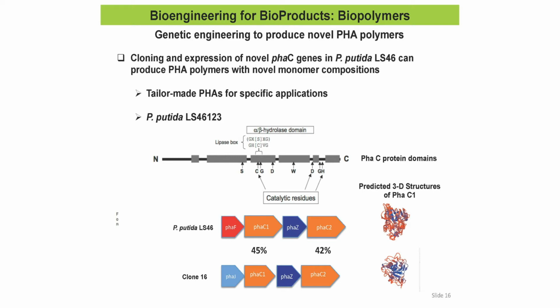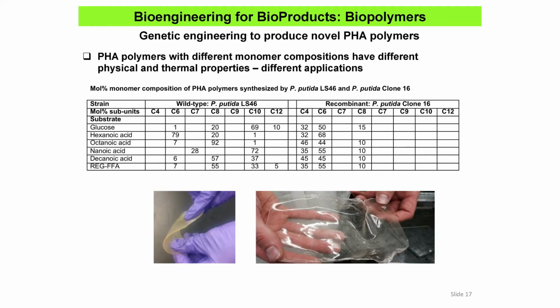If we look at the predicted three-dimensional protein structure of the endogenous PHA synthase, it looks like this. And the predicted three-dimensional structure of the cloned gene looks like this. So you can see immediately from the three-dimensional structure that they look different. And when we grew the bacteria on the substrates glucose, hexanoic acid, octanoic acid, nonanoic acid, decanoic acid, and free fatty acids from biodiesel production, using the wild type, we get polymers with different compositions, right? So if you grow it on glucose, we get almost 70% C10 and 20% C8 subunits, and a little bit of C12. If we use hexanoic acid, it's like 80% C6, 20% C8. Octanoic acid is over 90% C8 and a little bit of C6 and C10, et cetera.